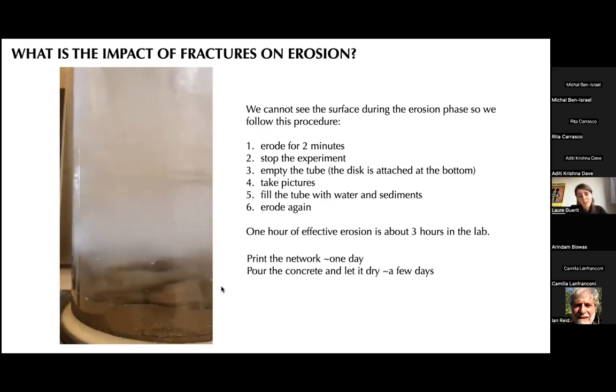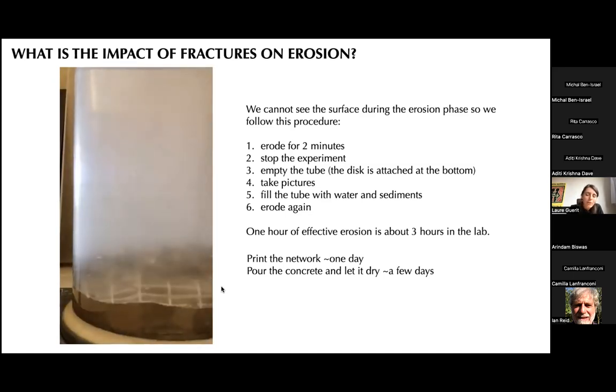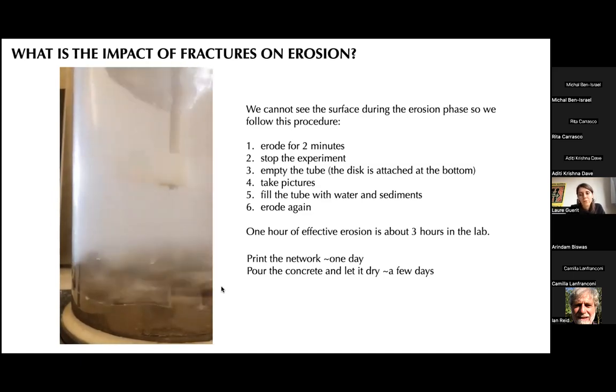So to perform the experiment, we erode the disc for 2 minutes, then we stop the experiment, we empty the tube, we take the pictures, we fill the tube again with water and sediment, and we erode again. So each experiment lasts about 1 hour of effective erosion, but it is in total, let's say, 3 to 4 hours of work in the lab minimum.